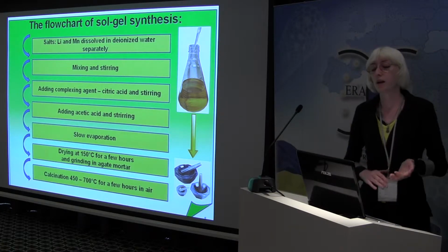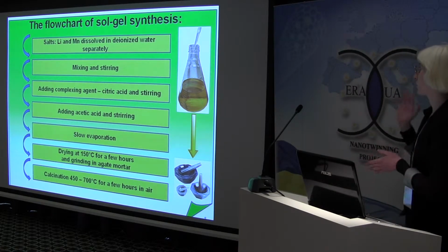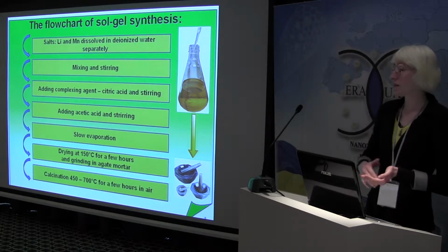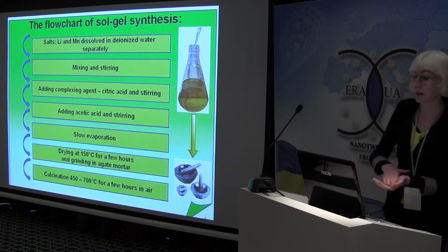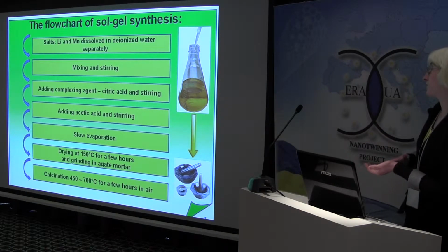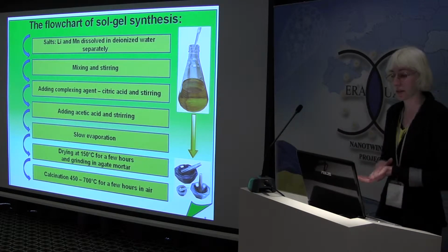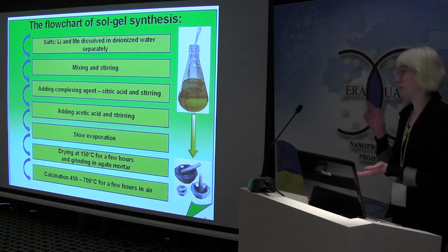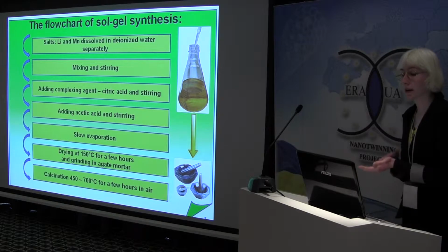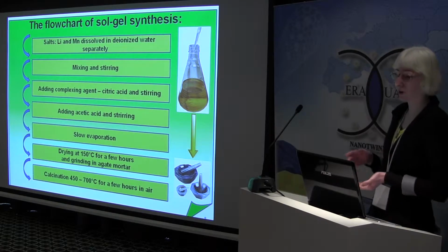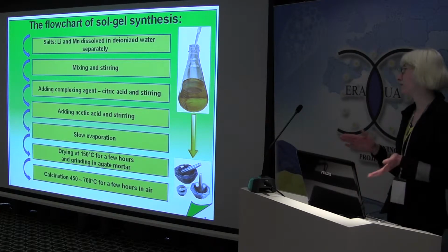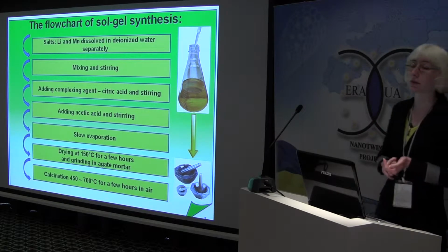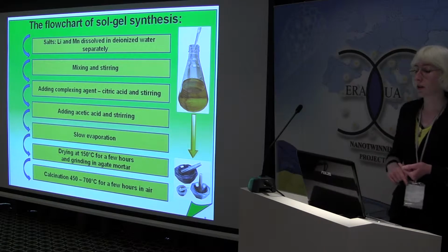In the first step, I dissolve lithium and manganese salts separately in deionized water, then mix and stir, adding complexing agents, citric acid and acetic acid, and mix and stir. The next step is slow evaporation, drying at 150 degrees for a few hours in air and grinding in an agate mortar, and here we obtain the preheated powder, the so-called xerogel.